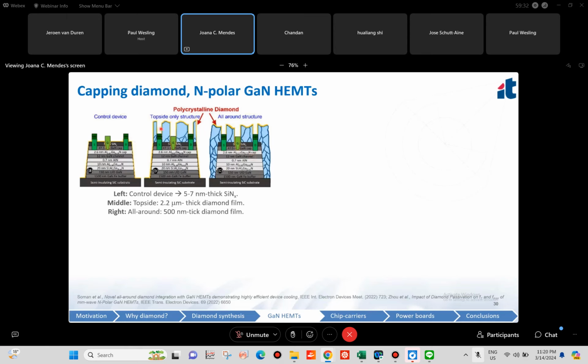And these researchers used two different approaches. In the first case, they did what Fujitsu did. They deposited micron thick films, in this case, 2.2 micron thick diamond film on top of the structure. And in the other case, they coated the whole mesa structure with a thin layer, 500 nanometer, of diamond all around the device. So they created a short circuit, a thermal short circuit, so to speak, that allows the heat to flow from the top of the device all the way down to the semi-insulating silicon carbide substrate.